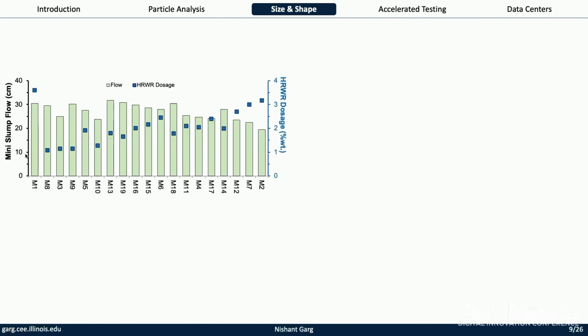Essentially, we made a bunch of UHPC mixes. This was a project where we wanted to make ultra-high performance concrete, which is 4 times stronger than your general concrete. So if your general concrete is 4,000 PSI, this could be 18,000 PSI, 20,000 PSI. And there's a huge potential for this material. You can now replace steel. You can have concrete without any rebar with this material, right?